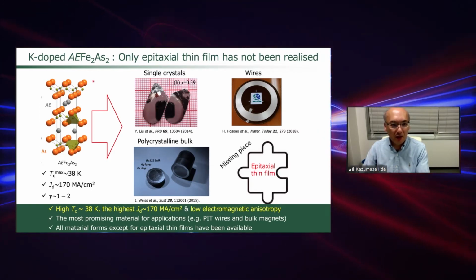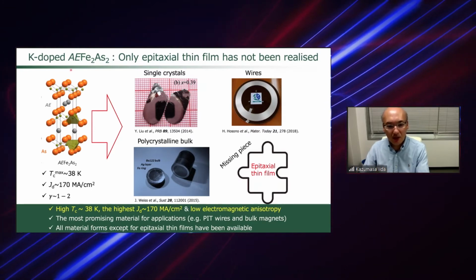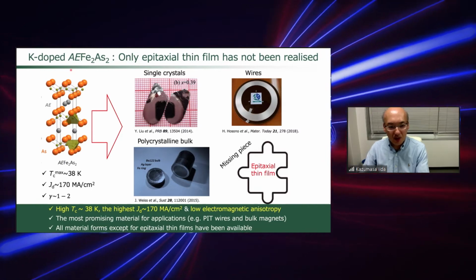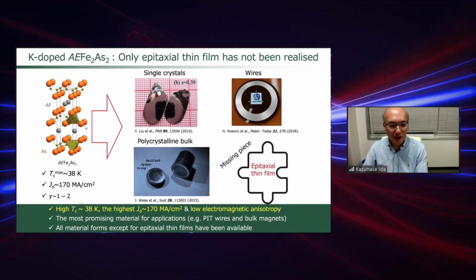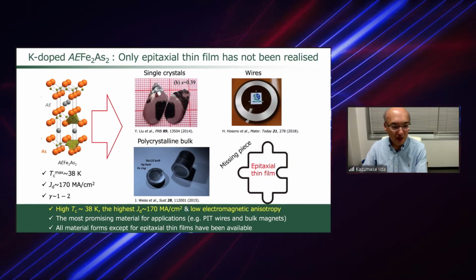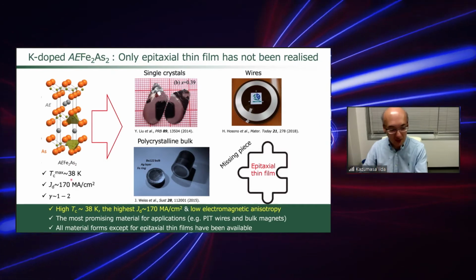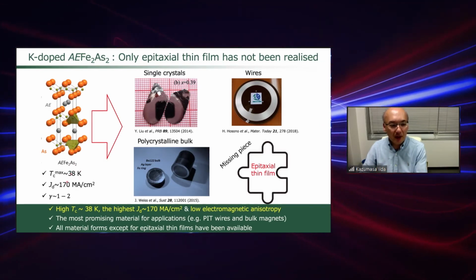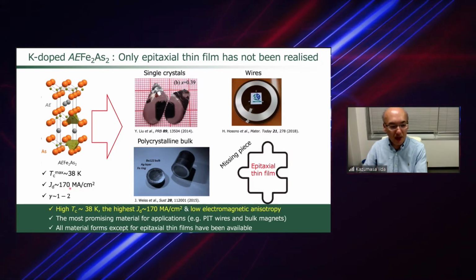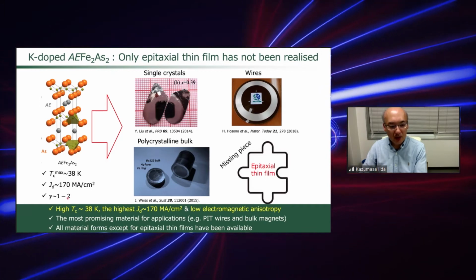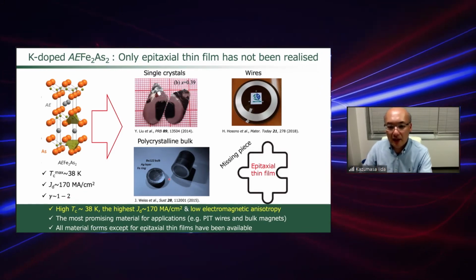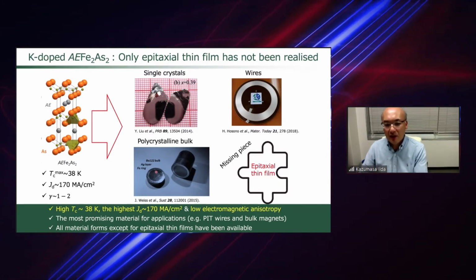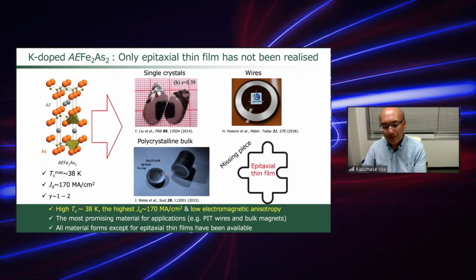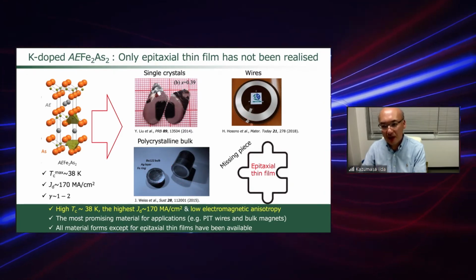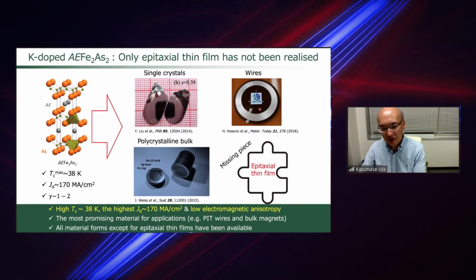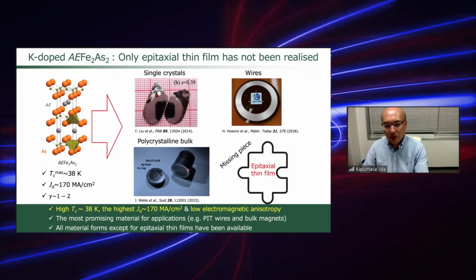But as I mentioned before, potassium-doped 122 is the most important material for applications. So we should somehow improve the critical current density of this material, because it is so attractive: the Tc is quite close to MgB2, the depairing current density is the highest among the iron-based superconductors, and it also has low electromagnetic anisotropy. Because of these good properties, many people are trying to make bulk magnets as well as powder-in-tube processed wires as proof-of-principle studies for the applications.